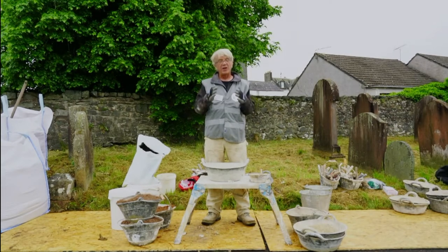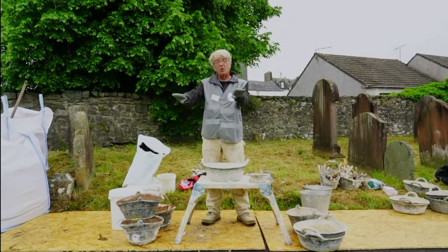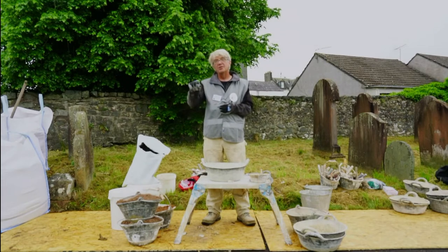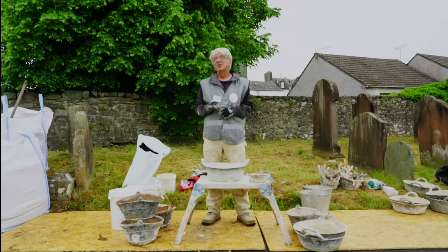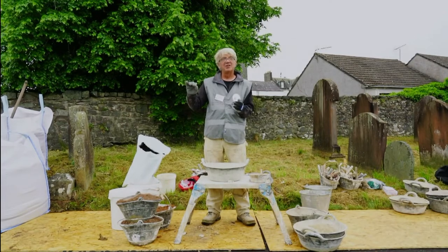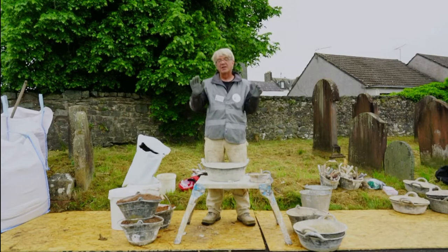That we had the workability, therefore the water retentivity, therefore the full extent of bond. And they are very adamant that you could have the most porous material in the world, as long as that bond is to a full extent, no water is going to get in to speak of. Whereas you could put the hardest, least breathable material in there instead. Common sense might say that's a good idea to keep the rain out, but the building just gets soaking wet very quickly because of all these things.